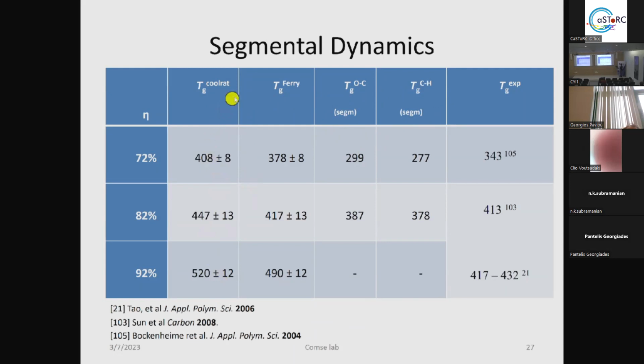And I applied after that the Ferry approximation, which was introduced by J.D. Ferry, who said that from these brute force cooling rate methods we may have some errors, typically numerically speaking. And in order to minimize these errors, I applied the approximation, which depends on the order of the cooling rate, in order to have the final values with the least possible errors. And of course, at the right, you can see the experimental values.